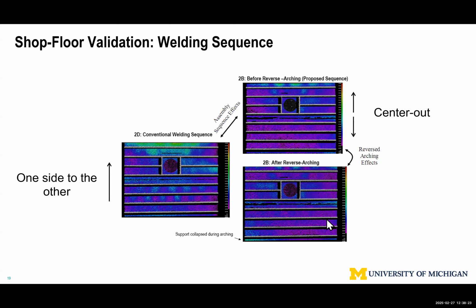And then we can also use the reverse arching, stretching the plastic zone, the shrinkage zone, without getting into detail, almost all gone, satisfying all requirements, except by that time, because when we do reverse arching, we bought this 2x4 wood block from a Home Depot near the shipyard. By that time, the 2x4 wood cannot support it anymore, collapsed. Okay, this part caused some damage. Otherwise, this panel is perfect from their dimensional accuracy acceptance criteria point of view.